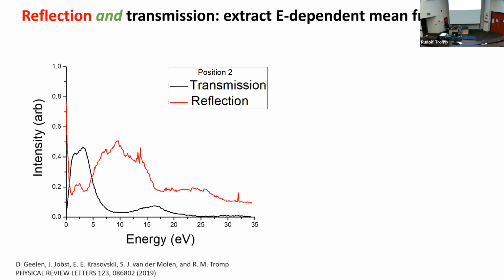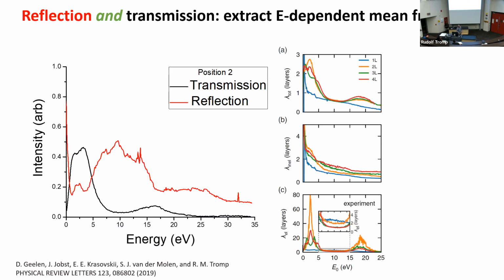We can now extract the mean free path. There's the total mean free path, how far the electron can travel at a given energy. And what is interesting, this is for one layer. When the layer gets thicker, it can actually travel further. You see 2, 3 layers are longer mean free path than one layer. Why? Because we've created this highway for the electrons to travel on at that energy. The inelastic mean free path is just 2 or 3 layers, right?